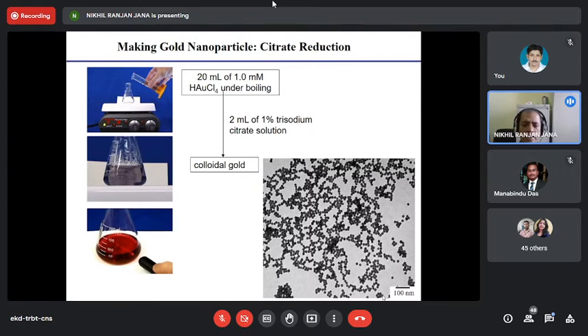And at the initial stage, the color is a little bit dark violet, and with time, particles are attaining the correct size. It's roughly 10 nanometers. Colloidal gold. You know, the method was developed long ago by Turkevich, and we still use it. A little bit of modification, perfection. It's a beautiful particle you can make. And by varying the amount of trisodium citrate, you can control size from 10 nanometers to 50 nanometers.